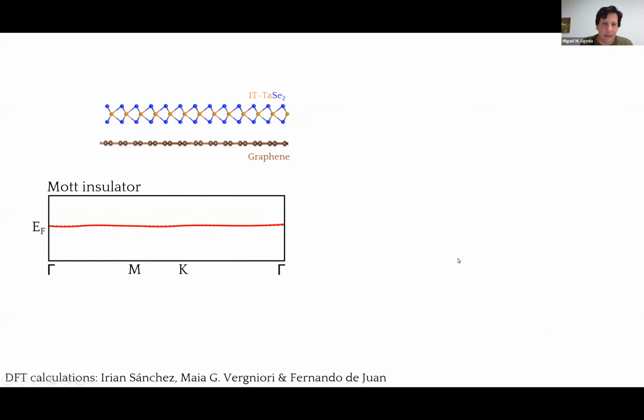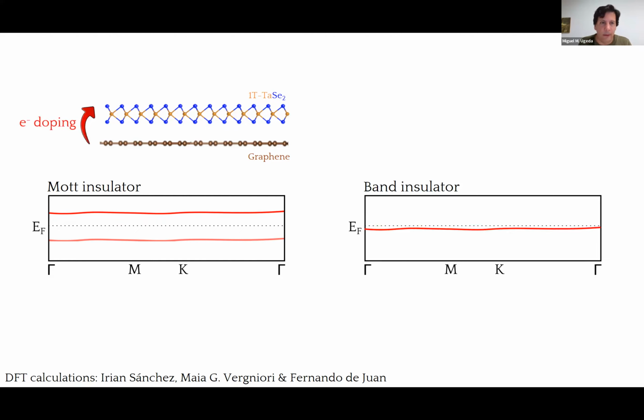So we are carrying out DFT calculations in order to disentangle this problem, because basically if we had a Mott insulator and we have now correlations, we would have something like this, and this is compatible with the existence of magnetic moments. But if for whatever reason there is some electron doping from the substrate, in this case graphene, to the 1T phase of tantalum dichalcogenide, the band would be filled, and therefore there would be no correlations and no isolated magnetic moments, and therefore the system would be a simple band insulator. So this is something that we are still carrying out and investigating.